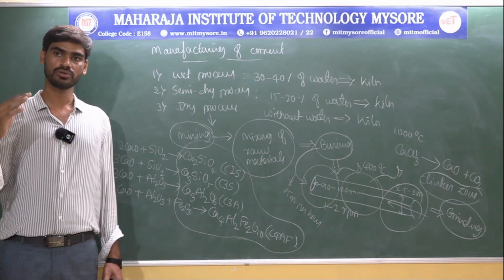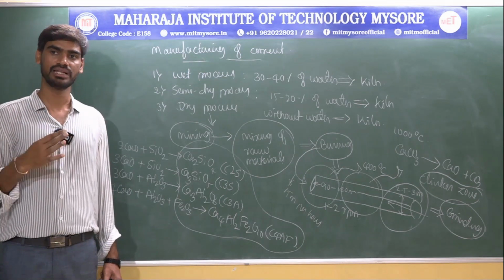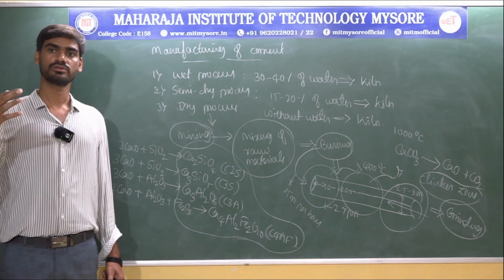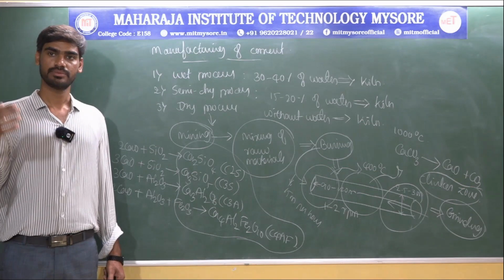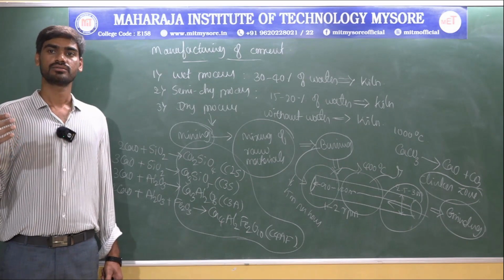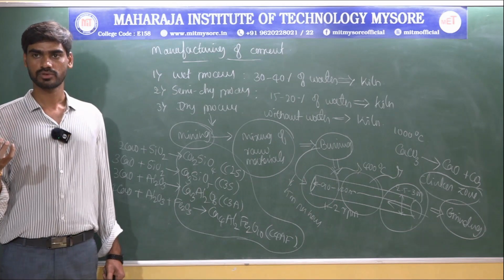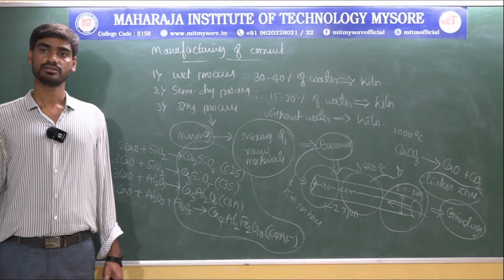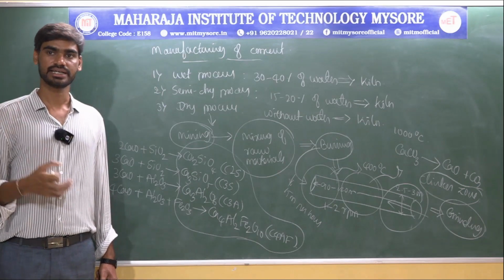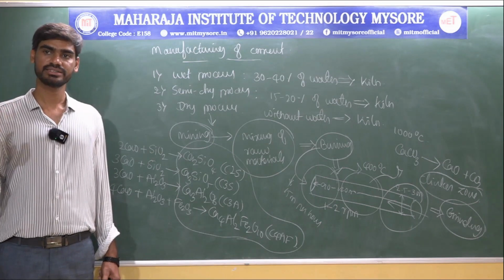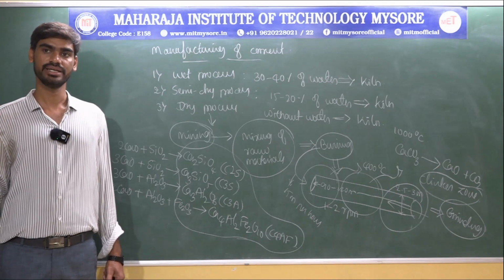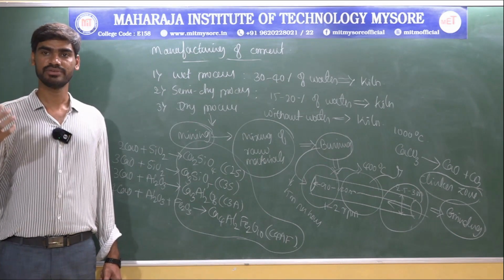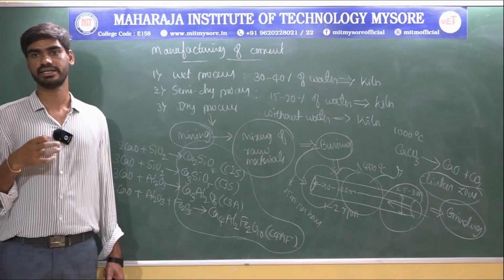The clinkers are ground finely into powder in a ball mill or tube mill. During the final grinding, at the end stage, the cement powder obtained is mixed with about 4 to 5% powdered gypsum, which acts as a retarding agent. Gypsum, we know, prevents the dissolution of tricalcium aluminate by generating tricalcium sulfoaluminate, which is insoluble, and prevents too early a subsequent reaction of setting and hardening.